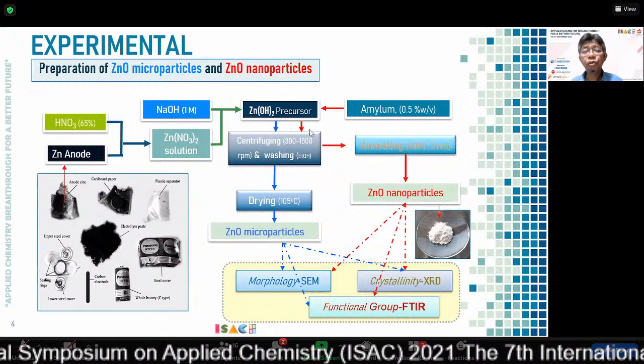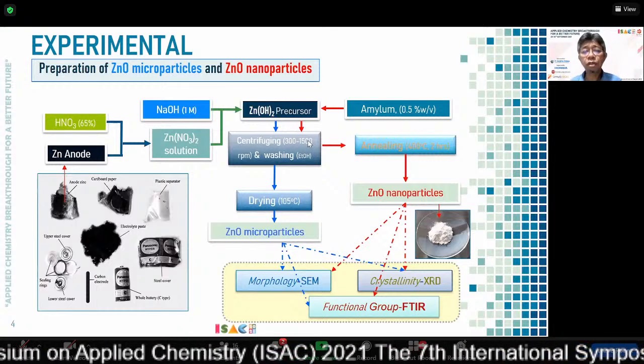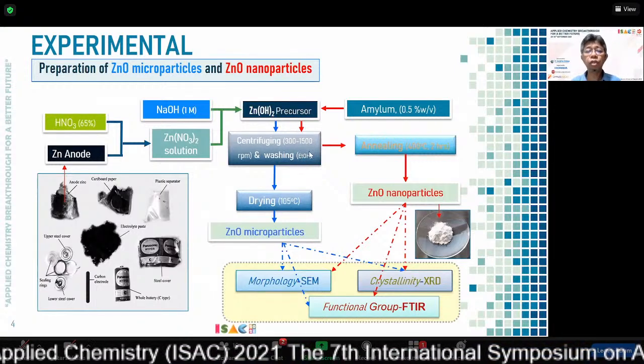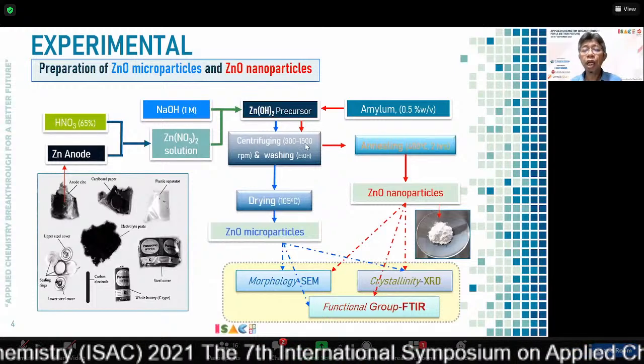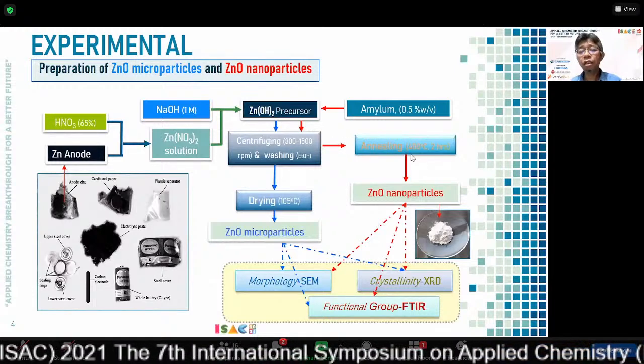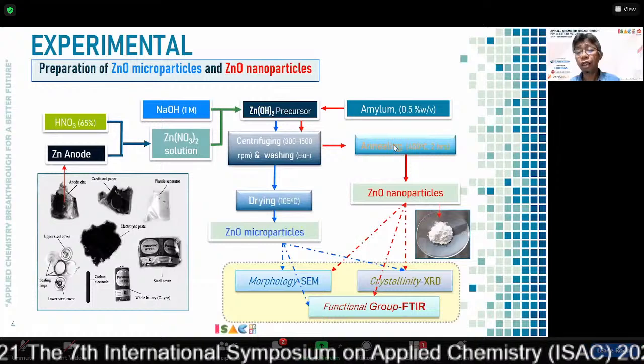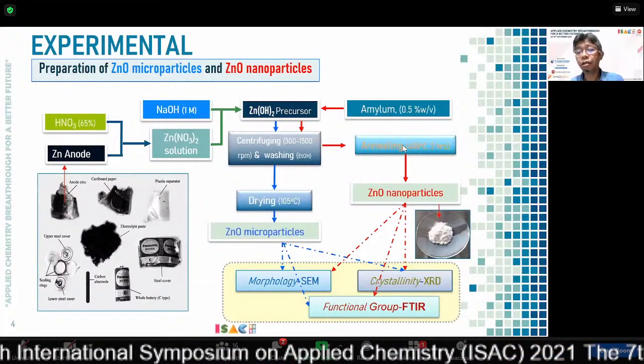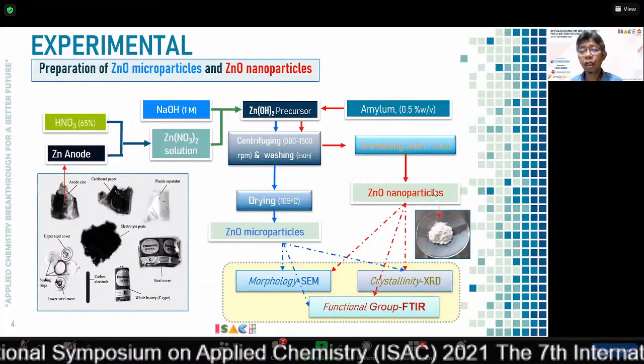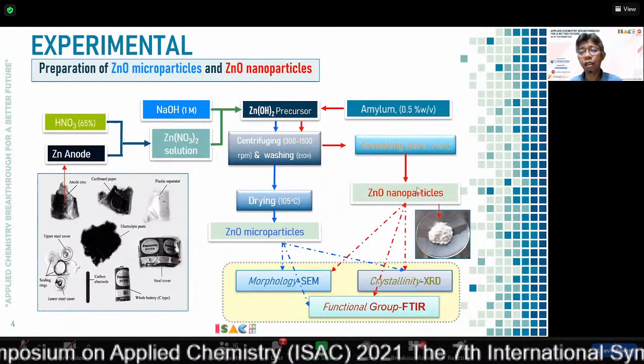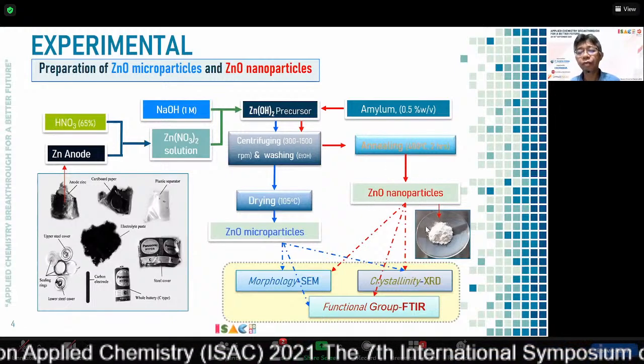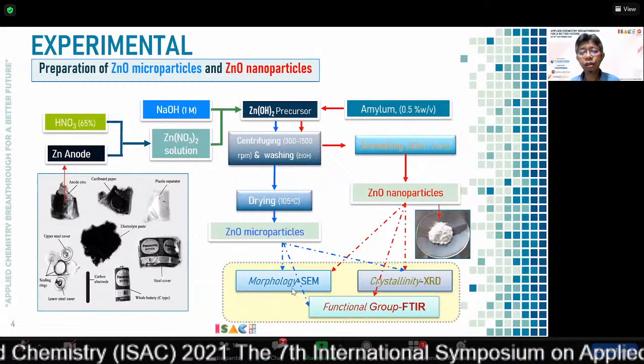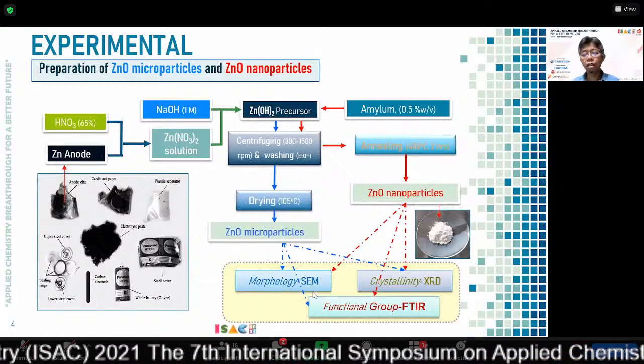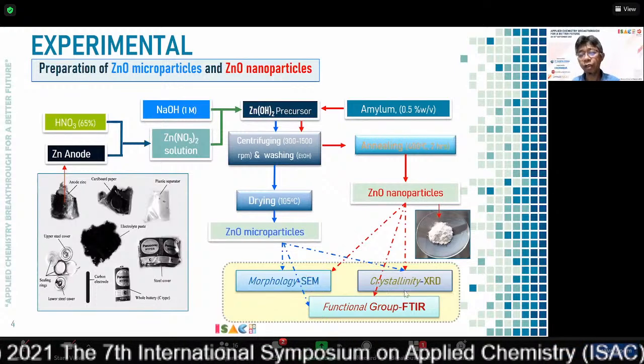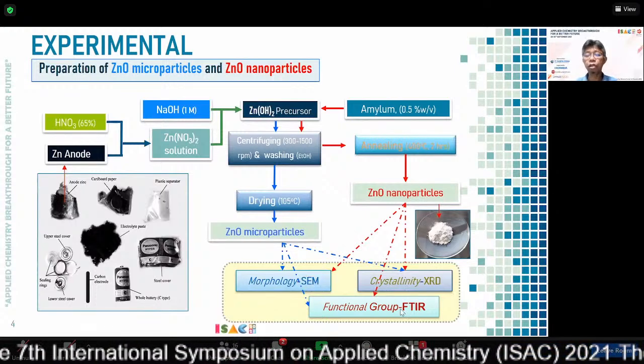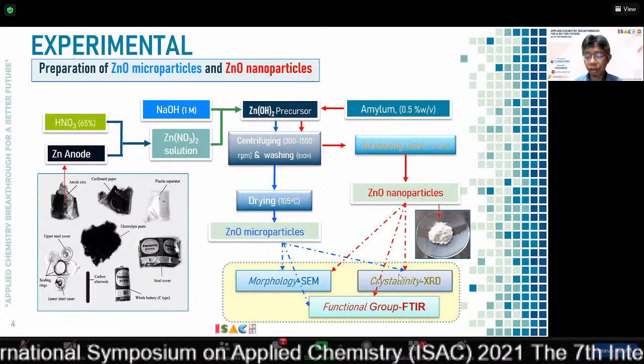We separate using a centrifuge, and then the product was washed with distilled water and ethanol, and then we calcine at an annealing temperature of 400 degrees centigrade for 2 hours. And then once we get the zinc oxide nanoparticles, as shown here, both materials were characterized by scanning electron microscope, XRD, and also Fourier transform infrared spectroscopy.